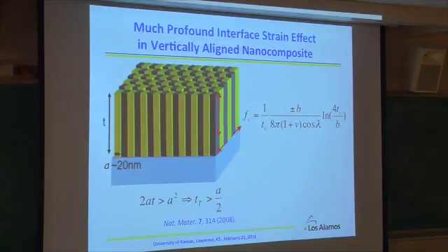Another thing, the beauty, if you think about this one, is if you do single phase material, when you grow a one layer material on a substrate, due to the lattice mismatch between the substrate and the film I mentioned earlier, typically you have a critical film thickness. Beyond the critical film thickness, the energy build up across the interface is so high, they have to relax. You form the misfit dislocation right across the substrate and the film. However, when you do this, you can think about it, it's a vertical interface. If you have two phases of material, one material controls another.